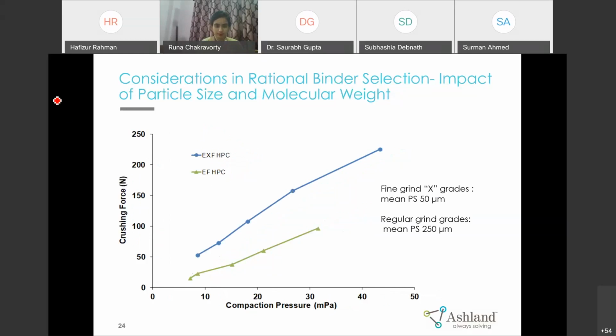Now another thing is particle size. What we have done is manufacture two batches. One batch with EXF, which is the finer grade, and another batch with EF, which is the regular grade. We compressed tablets at different compression forces and checked the tablet hardness. At all the compression forces, we found that the tablet containing the finer grade, EXF, gives better compressibility, so better hardness. It clearly tells us that if we use a finer grade, we can get better tablet hardness.